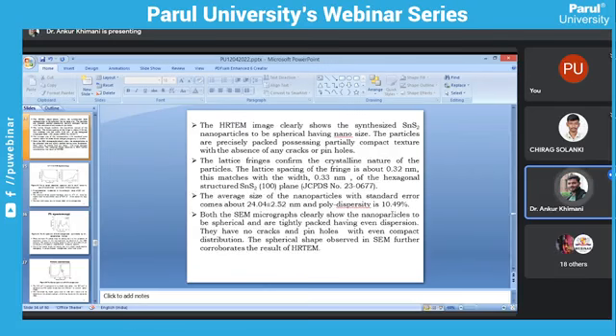The HRTEM image clearly shows the synthesized SnS2 nanoparticles to be spherical, having nano size. The particles are closely packed, possessing a partially compact texture with absence of any cracks or pinholes. The lattice fringes show the crystalline nature of the particle. The lattice spacing of the fringe is about 0.32 nanometer. This matches the d-spacing 0.33 nanometer of the hexagonal structure SnS2 100 plane.